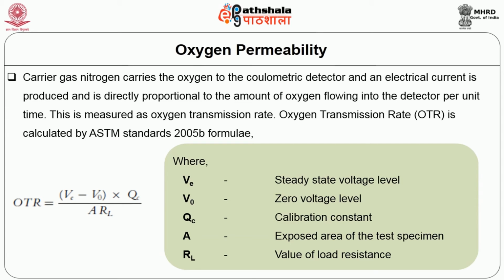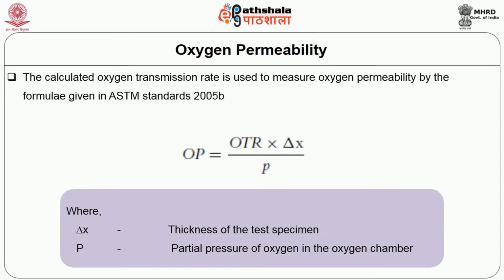OTR is equal to (V_E minus V_0) into Q_C divided by A into R_L, where V_E represents steady state voltage level, V_0 represents zero voltage level, Q_C represents calibration constant, A is the exposed area of the test specimen, and R_L represents the value of load resistance. The calculated oxygen transmission rate is used to measure the oxygen permeability, again using the formula given in the ASTM standard, as OP is equal to OTR into del x divided by P, where del x represents the thickness of the test specimen and P represents the partial pressure of the oxygen in the oxygen chamber.